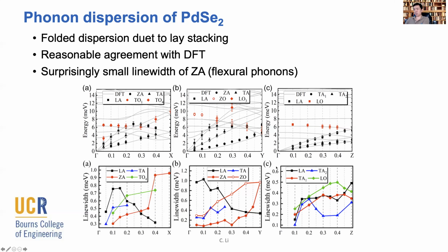and the phonon dispersion itself usually seems to show a quadratic type of dispersion relation. And the one thing we did observe that we think could be interesting is when we try to extract the phonon line width, which will tell us information on the phonon lifetime in this material, we find that this ZA mode, this flexural mode, has a quite narrow phonon line width. As you can imagine, inelastic x-ray scattering doesn't have very high energy resolution, so a lot of the fittings probably won't tell you much, since our instrument resolution is usually on the order of meV, but it does clearly indicate that we have a narrower phonon line width for this ZA mode in comparison with the others. So we don't know exactly what the line width is, but we do know that it's narrower. And this is kind of interesting to see.